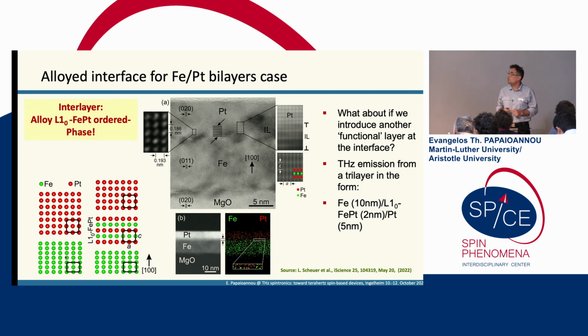So what else did we try to do? We took our platinum bilayer and tried to grow an alloy at the interlayer. And we managed to grow this L10 ordered phase of iron platinum.